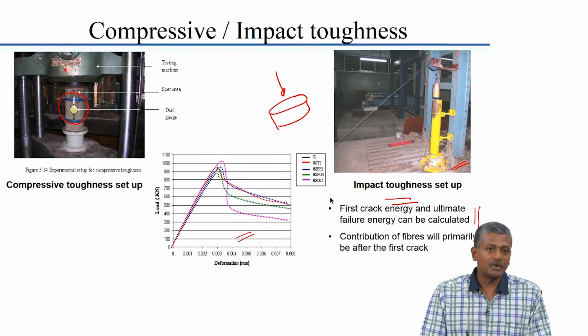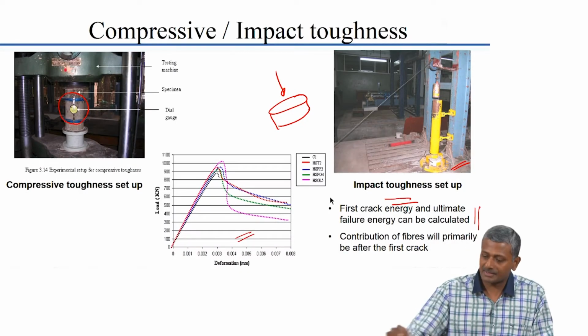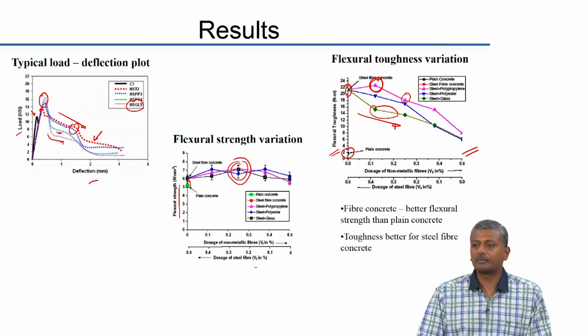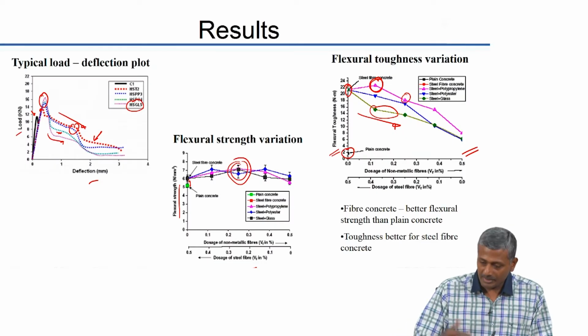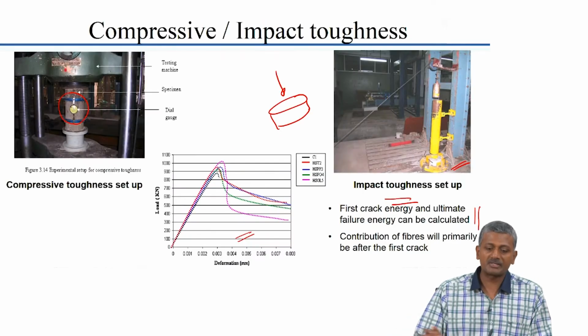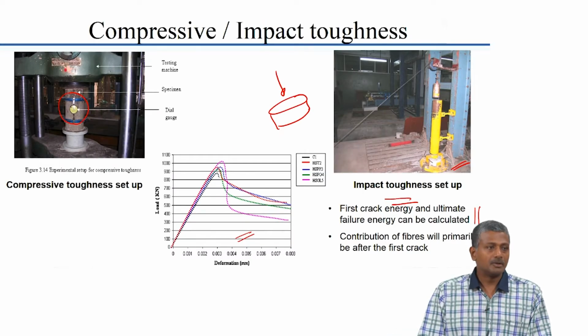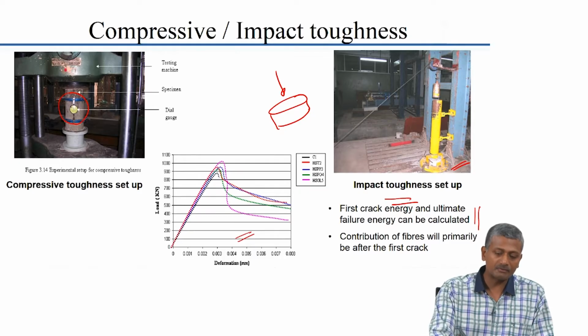So, let us resume our discussion on compressive and impact toughness that we were talking about in the last class. Here we were trying to investigate the influence of combinations of fibers, hybrid fibers, essentially looking at combinations of steel and non-metallic fibers on the properties of concrete, and we investigated through a semi deflection controlled approach the toughness of fiber reinforced concretes as they were affected by the presence of steel fibers and other non-metallic fibers in the system. The same experiment was repeated, as I said, with compressive and impact test setups, but of course, the degree of control in the compressive setup was not very good.